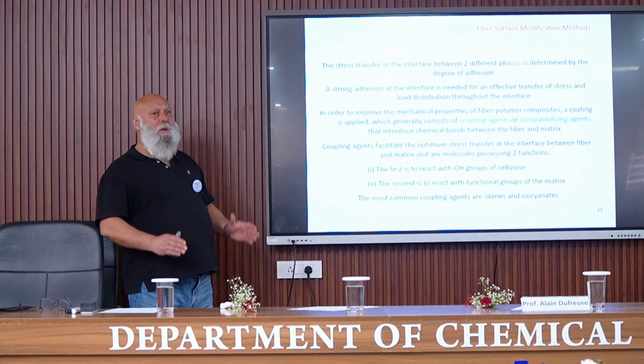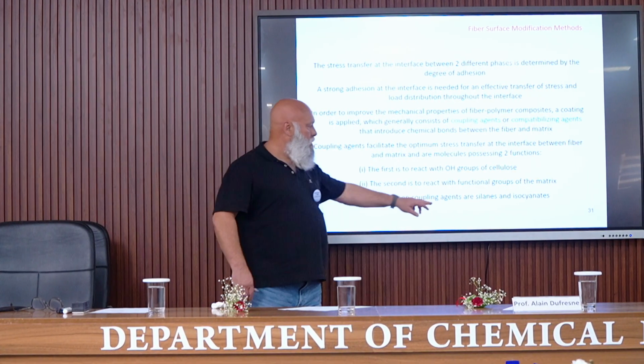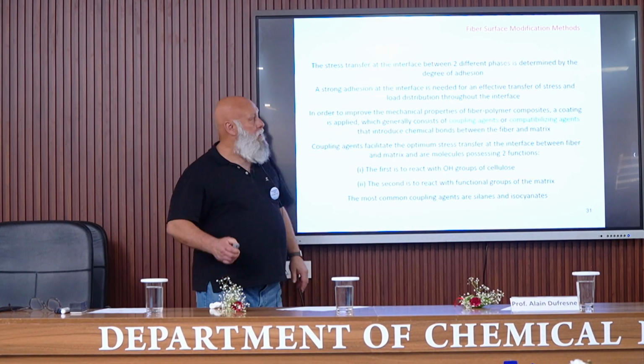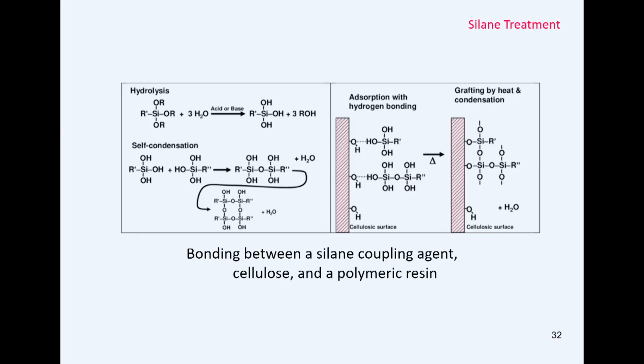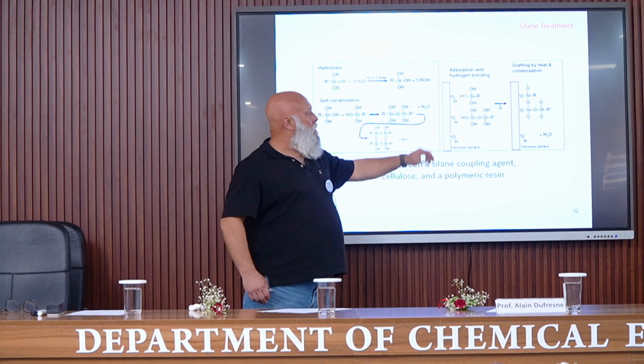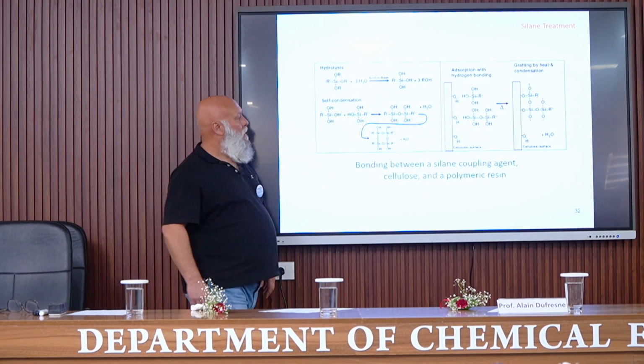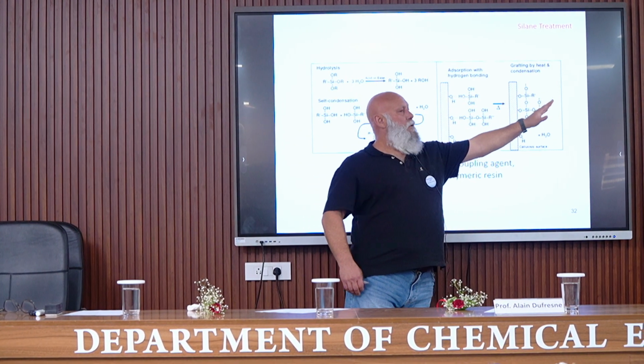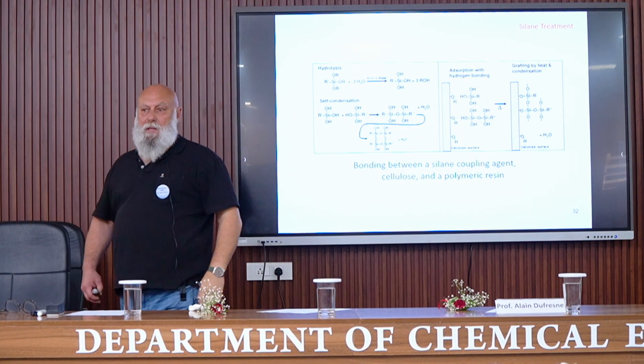So there are mainly two families of compatibilizing agents which are used, which are called silane and isocyanate. So you can see here the process of compatibilization when using a silane agent. So it is this kind of molecule that reacts first with water, and then there is a self-condensation process, and then hydrogen bonding that promote interaction or adsorption to the natural fibers, and then by increasing the temperature, a chemical grafting. So we have this chemical grafting, and you can see that the outer part of the fiber is now more hydrophobic.